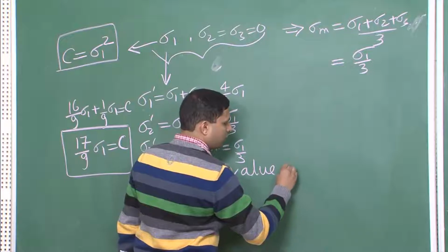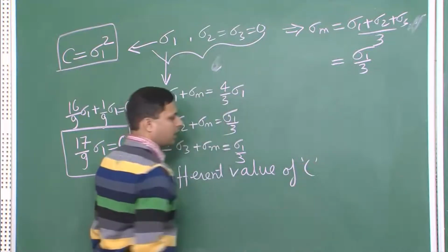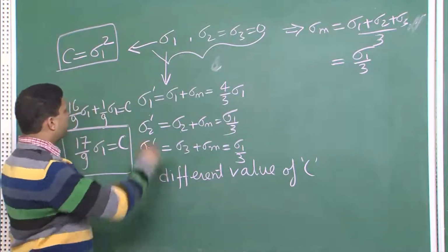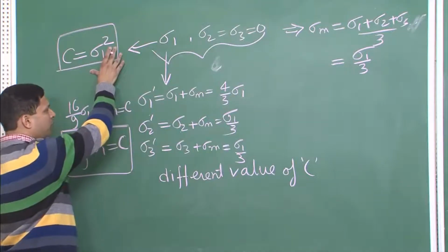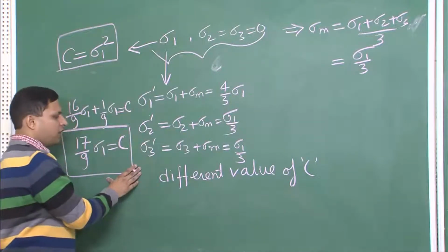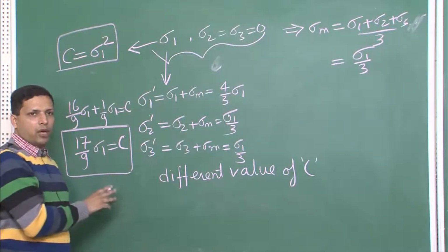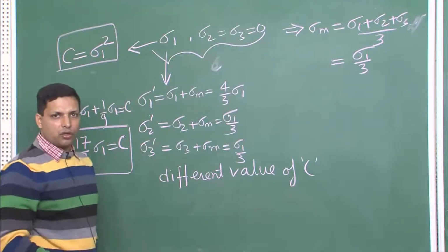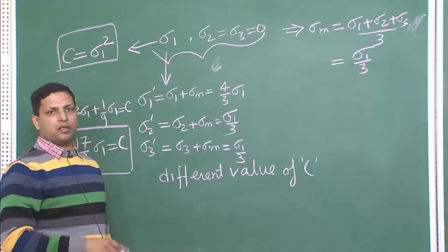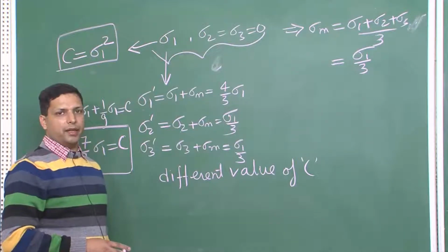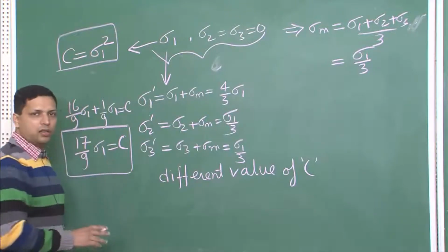In effect, what it is saying is that the material will deform differently, or under different conditions, before applying mean stress, and the material will deform differently, or the onset will take place at a different value, when you have applied mean stress. But we know this is not true. We know that mean stresses do not influence yielding. Therefore, this criterion is not valid.